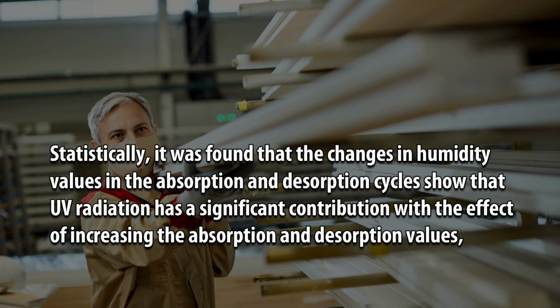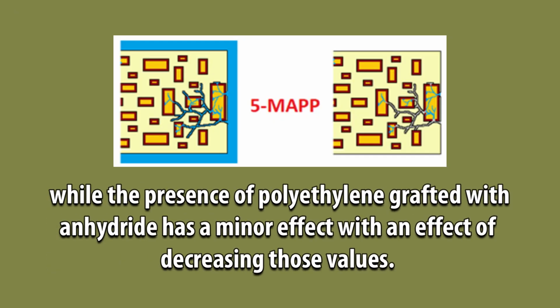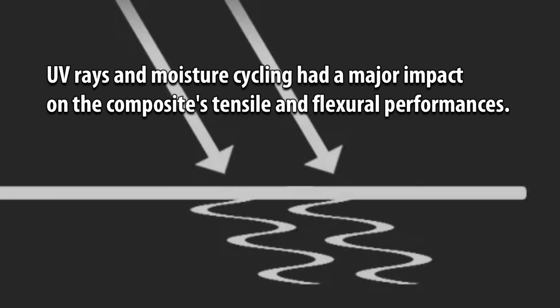Statistically, it was found that the changes in humidity values in the absorption and desorption cycles show that UV radiation has a significant contribution with the effect of increasing the absorption and desorption values, while the presence of polyethylene grafted with anhydride has a minor effect with an effect of decreasing those values. UV rays and moisture cycling had a major impact on the composite's tensile and flexural performances.